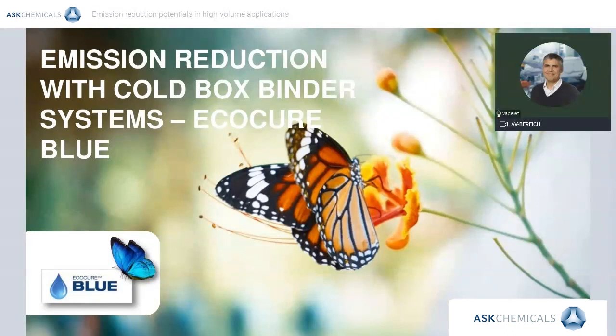Polyurethane Colbox resins used in foundries are the result of a polymerization reaction between the formophenolic polymer content in Part 1 and the isocyanate content in Part 2. Polyurethane is a 100% organic carbon-based plastic which releases volatile products into the atmosphere and which, during the casting process, burns and emits polluting products. If all Colbox are defined in this way, it is possible to limit this emission. The best system for this at present time is most certainly the EcoCure Blue family.